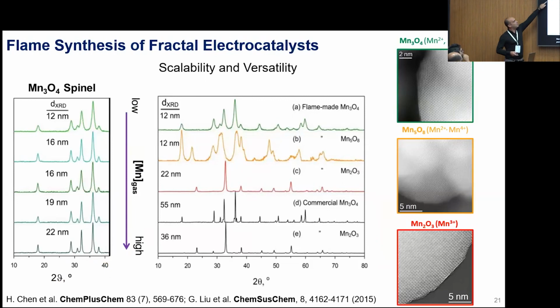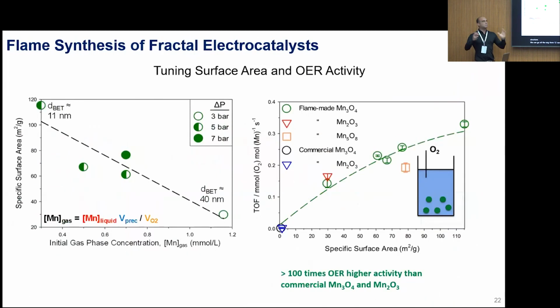And we can control very well the size and the structure. And we get polymorphs of manganese oxide. We can go all the way from 12 nanometer to 22. We can control the specific surface area. So how much surface area per gram is an important characteristic for catalysts, right? And we can go all the way from 30 square meter per gram to more than 120 square meter per gram continuously.